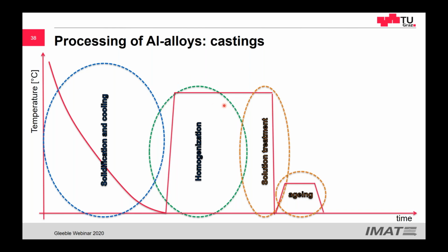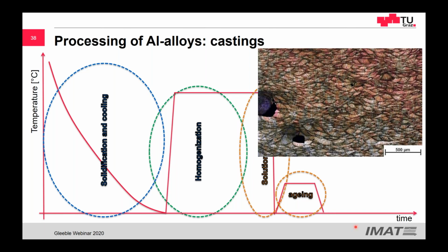Then they did homogenization, solution treatment, and aging. You can also avoid this homogenization step, and this is also many times done, and just do the aging step since the cooling rate is very fast. But of course, the cooling rate is very fast only for the first layer. Then the other layers are again some heat. This is the material they got.